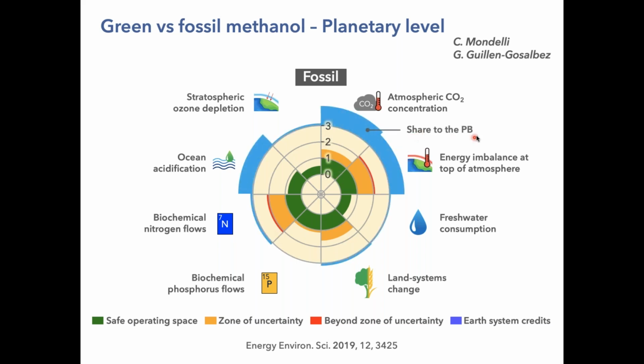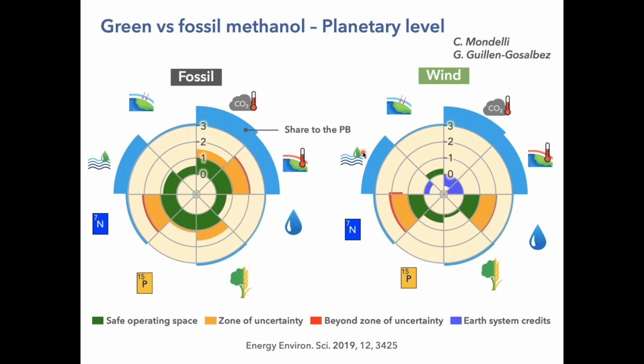It's important to deal with the share of the planetary boundary. And so the size of this blue region indicates how important that planetary boundary is to the overall assessment. So indeed, exceeding nitrogen flows is not so critical, because that planetary boundary has a little effect compared to the energy imbalance. So actually this is the problem in methanol synthesis from fossil fuels. And if you go into CO2 hydrogenation as a way to produce methanol, taking wind as a renewable energy source to produce green hydrogen, what you see is indeed that the planetary boundaries of global warming are actually satisfied.